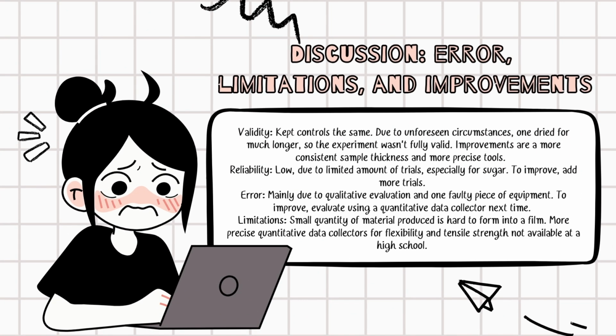Validity was attempted to be maintained by keeping controlled variables like heating temperature, drying time, and starch amount, etc. constant, and only changing the additive composition. However, due to time issues, the first glycerol sample ended up drying for almost 5 times longer than the others, so the validity was not necessarily upheld to the whole experiment.